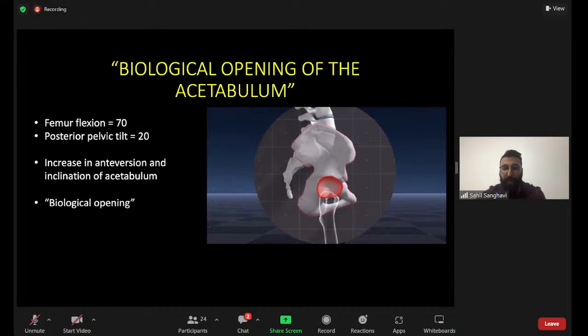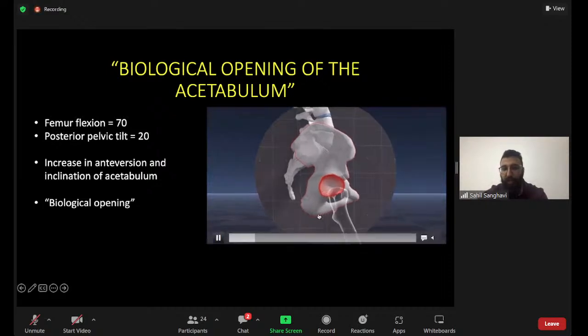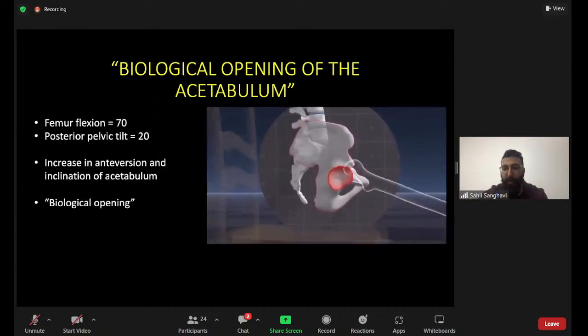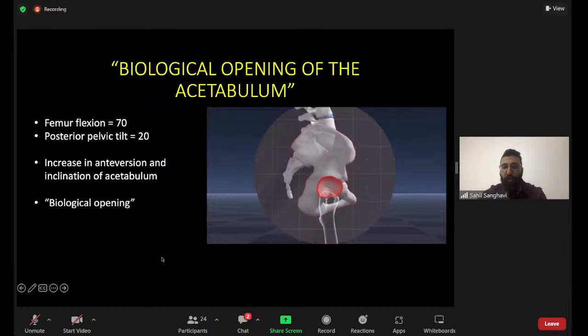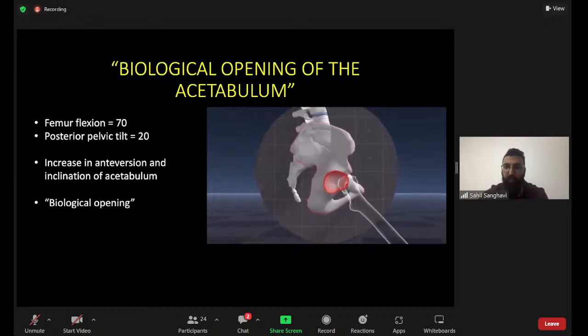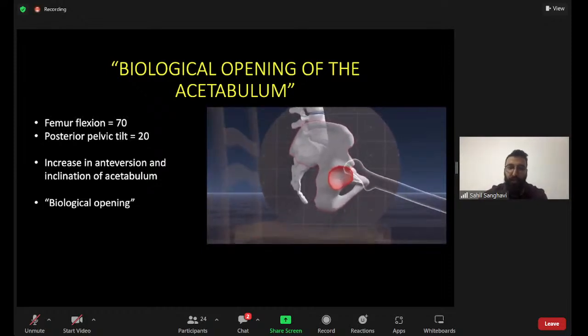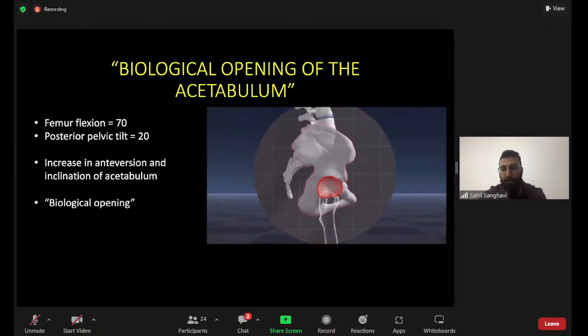Is that when you go from the standing to sitting position, it's not only your femur that is flexing 90 degrees. Your femur only flexes about 70 degrees, and the remaining 20 degrees is a tilt, or a posterior tilt, of the acetabulum, of the pelvis. So you can see in the video here, as you are going into flexion, the femoral head is moving in flexion, but the pelvis is also moving behind. So in patients who have a lumbar spine operated, you lose this 20-degree posterior tilt, which predisposes these patients to dislocation, where the real value of dual mobility is there.